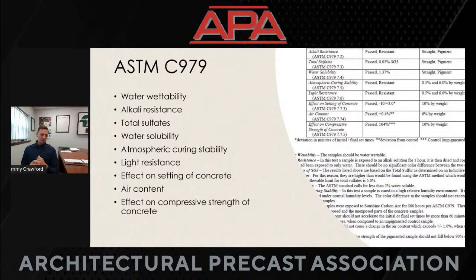Water wettability: you cannot have a hydrophobic iron oxide pigment in your mix. Why? Well, concrete has water in it, so you can't have oil going into your concrete, and it has to be able to mix with water. Alkali resistance: obviously, concrete is a very caustic environment. You can't have something that's going to break down in that environment. Total sulfates: obviously, for efflorescence issues, you can't be adding excessive sulfates into the mix.